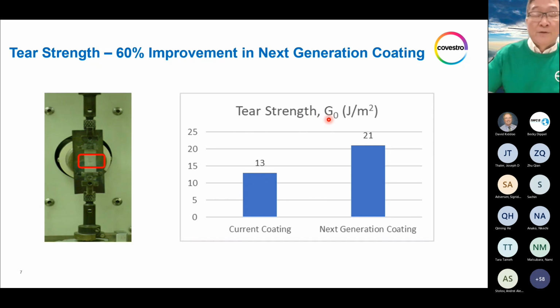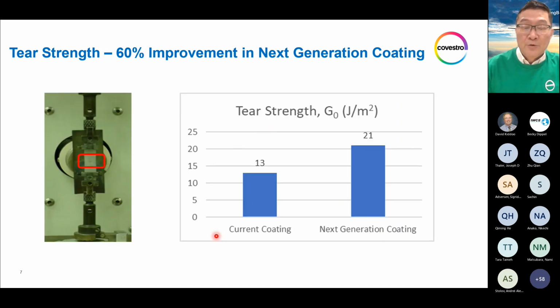So again, the focus here is not to talk about how to calculate G0. With this well-defined method by ASTM, we measured the cured primary coating tear strength of both the current coating, remember current coating, and the next generation coating. And tear strength actually increased from 13 joules per meter squared to 21 joules per meter squared, which is a 60% increase in tear strength.